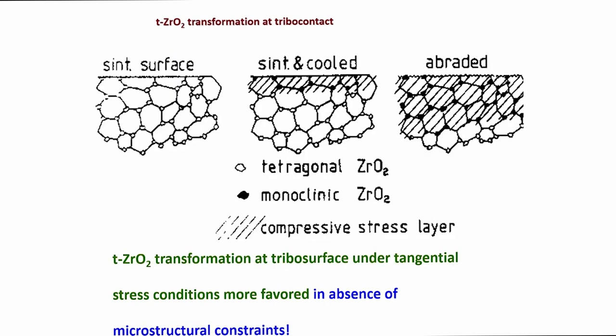Now, how do this microcracking and phase transformation take place? We are trying to explain this here with some similar reports from the literature, not exactly against the same counterbody, not exactly under the same testing conditions, but we believe the mechanism may be similar. So, suppose it is an as-sintered surface, like a hot-pressed surface, it is sintered but cooled, so there may be some phase transformation, and when it is abraded, there is a compressive stress layer that is formed.